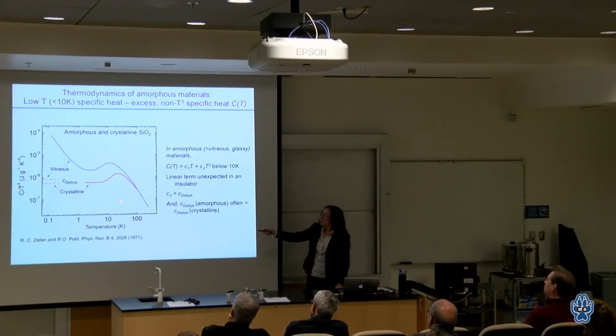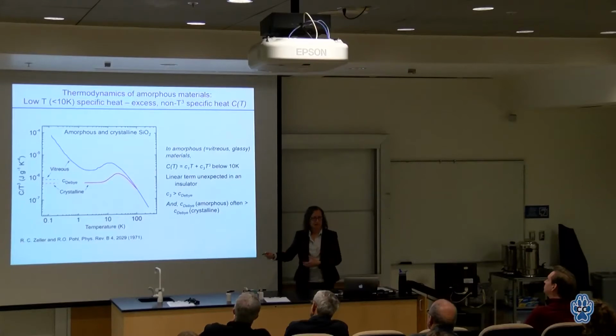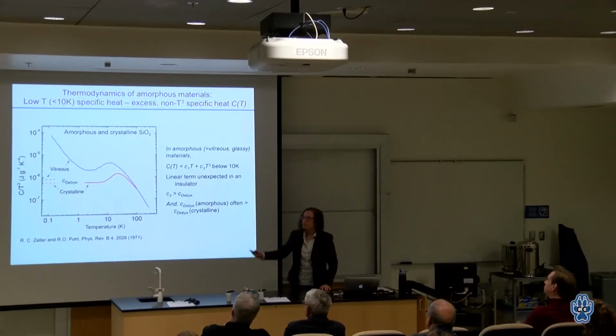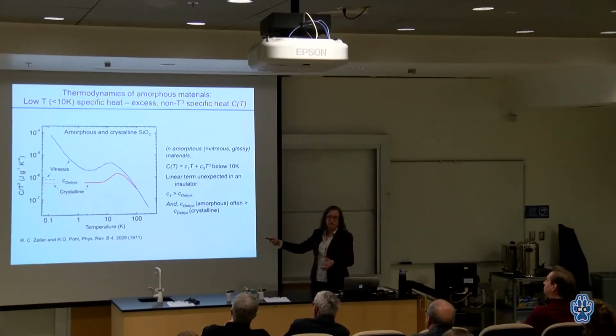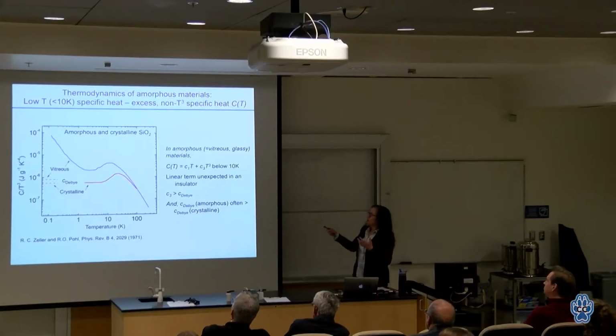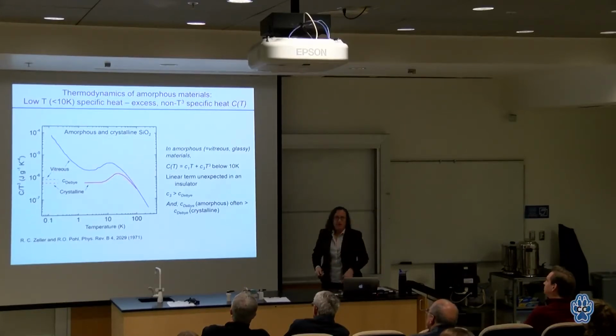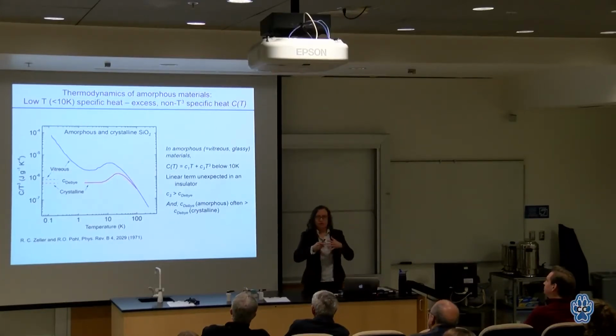This is a plot of C over T cubed to get rid of the T cubed dependence. What this shows is a linear term. Not huge, a linear term. A linear term will always look huge by the time you get to low enough temperatures. So where is that coming from? This is a temperature range where the phonons, the vibrations of the lattice, are at very long wavelength, and it should not matter the details of the crystal structure.